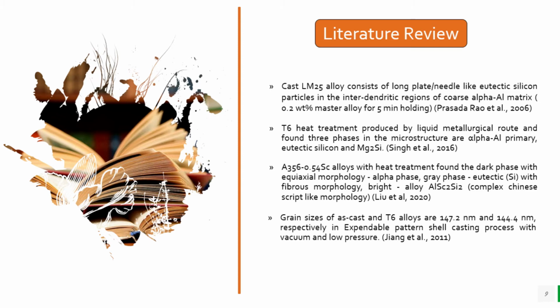Chinese script-like morphology. Lastly, from Jiang et al., they found that the grain sizes of the cast and T6 alloy are 147.2 micrometer and 144.4 micrometer respectively in expendable pattern casting process with vacuum and low pressure.